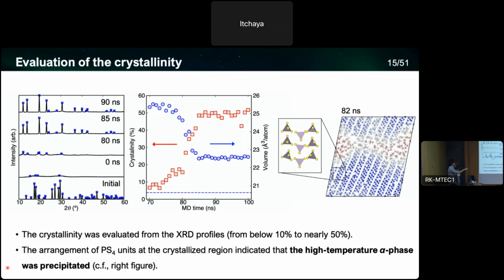At the beginning, the crystallinity is below 10%, which again shows that our structures are glass initially. And it goes to approximately 50%. Where the entire structure looks crystallized, the crystallinity is saturated at 50% because we have some defects inside the structures which prevent a further increase of the crystallinity. That is the current understanding. And if you look at the crystallized regions, the arrangement of PS4 units is like this, which is actually different from the initial crystalline structure. This is known as the high temperature phase, which we call the alpha phase. So by doing the heat treatment, what we obtained in the crystalline region is the high temperature phase.